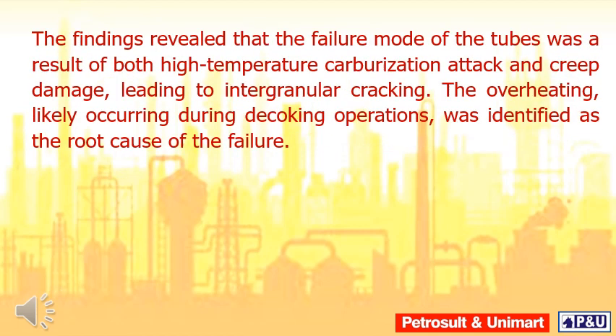The findings revealed that the failure mode of the tubes was a result of both high-temperature carburization attack and creep damage, leading to intergranular cracking. The overheating, likely occurring during decoking operations, was identified as the root cause of the failure.